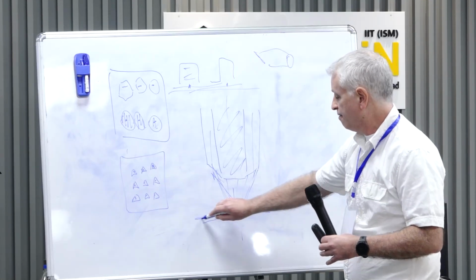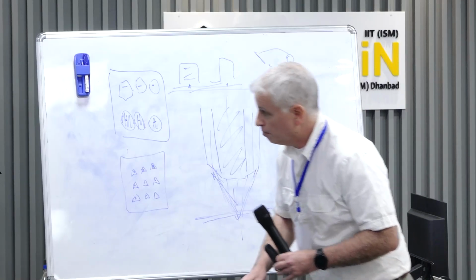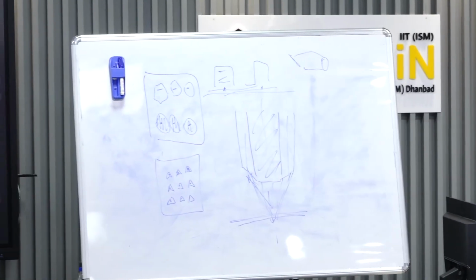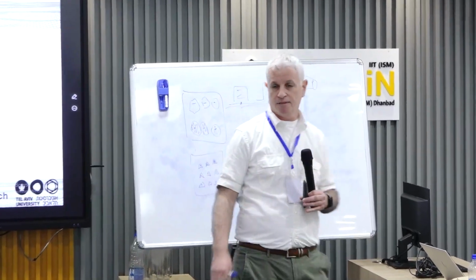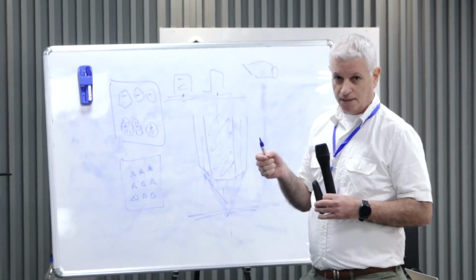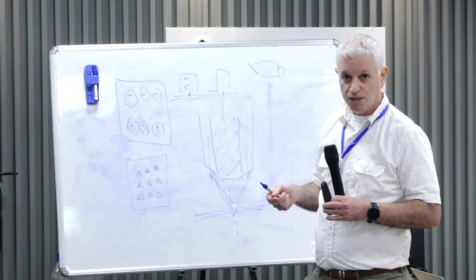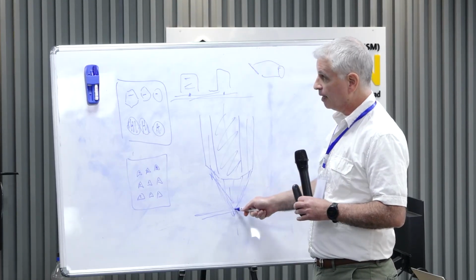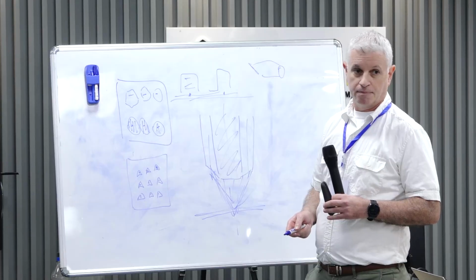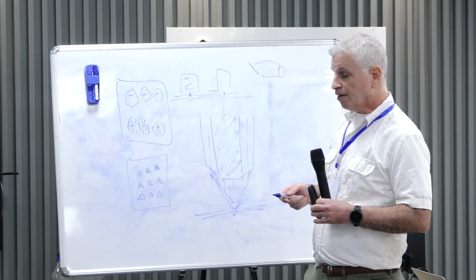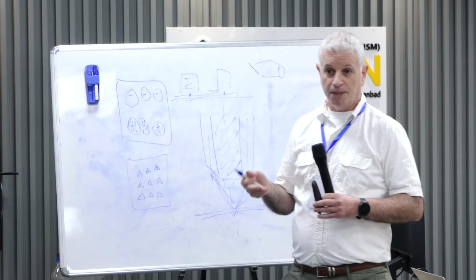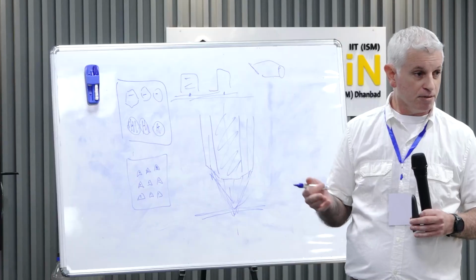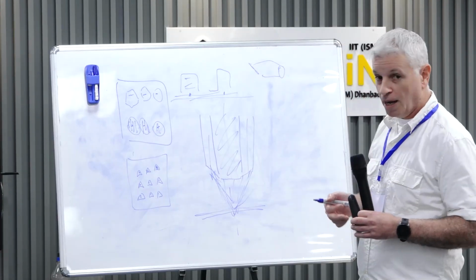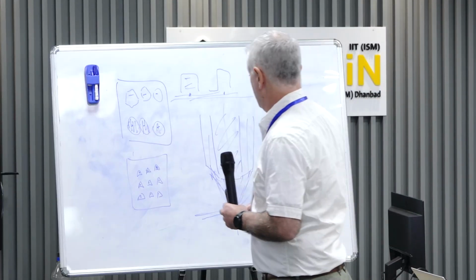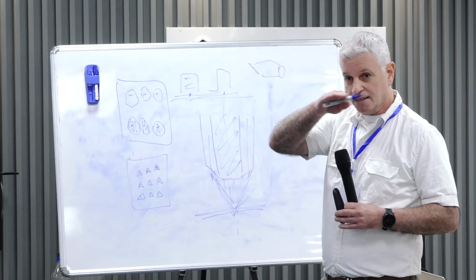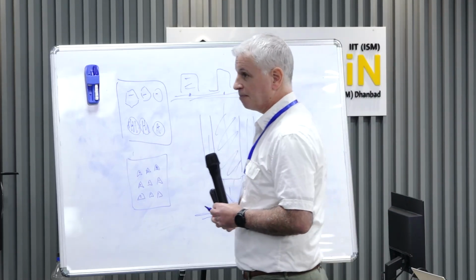So if you have a very flat surface, you will see black. You don't see anything. If you have asperities on the sample, even nanowires, nanoscale objects, they will scatter the light, and you will pick some of it up. Therefore, it's a very good method, even in optical microscope, to see if you have even nanoscale objects in your sample. And why am I telling this? It is not sensitive enough to detect a single atomic layer, but in this case you don't need it.